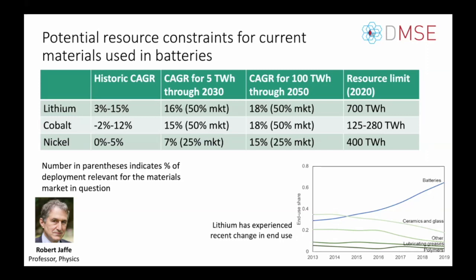So nickel is particularly of concern versus something like lithium. What I'm showing on the bottom here, over time, is the dynamics associated with the end use of lithium in batteries. This blue line shows that end use increasing to significant fractions, such that the mining supply chains have become more used to that market as an end use for extraction. Actually, I think there was just an article in the New York Times this morning, or maybe yesterday, about lithium growth domestically, which was interesting as well.